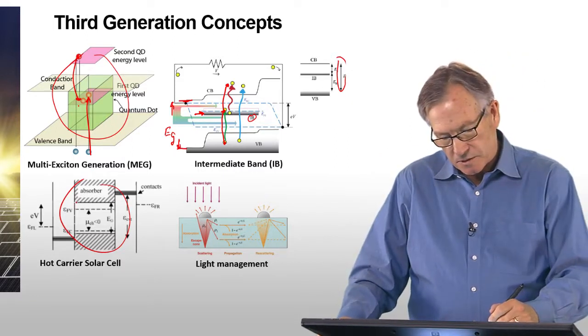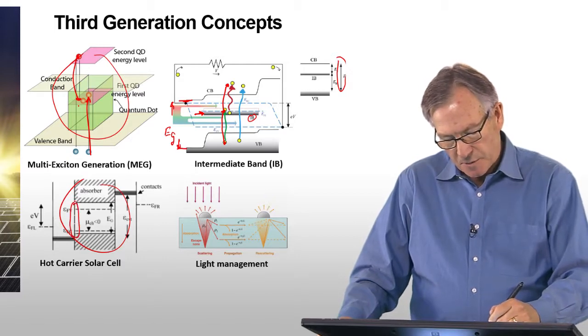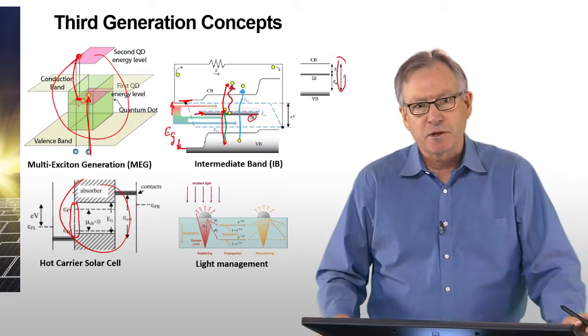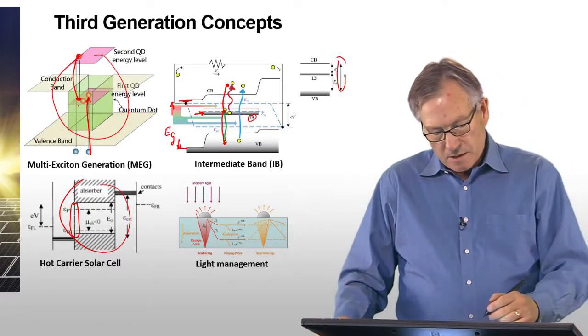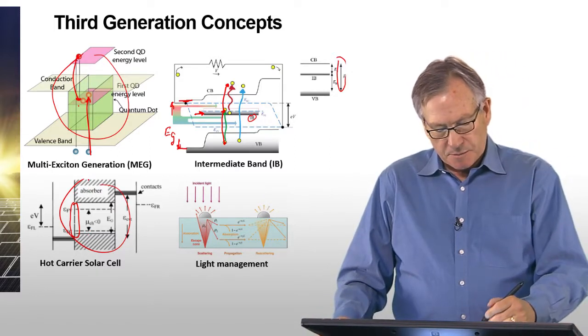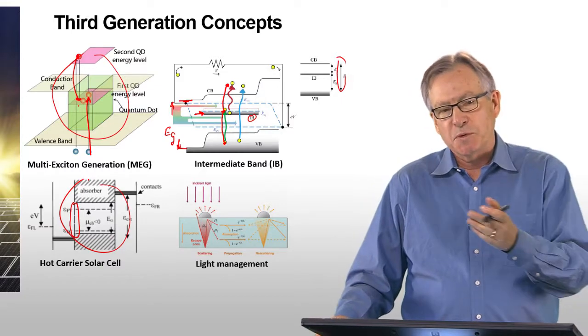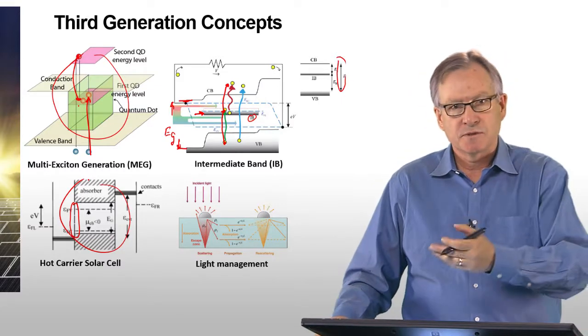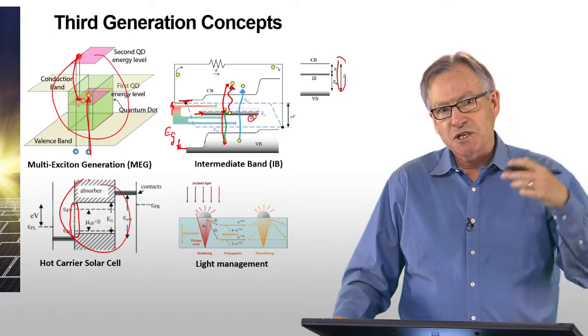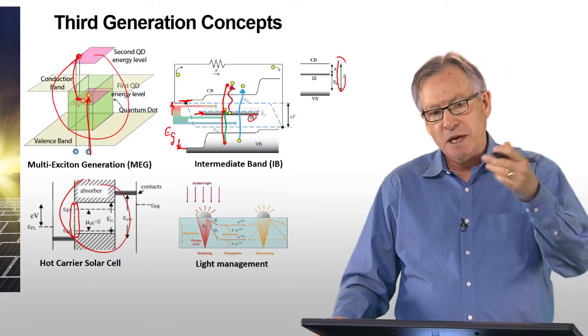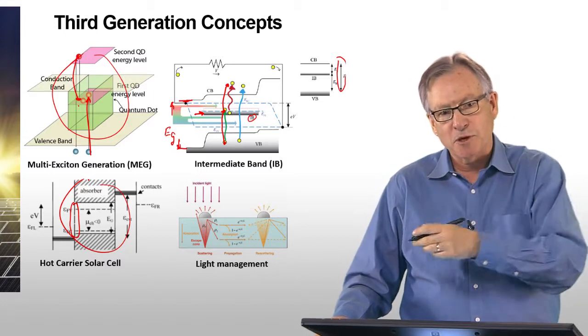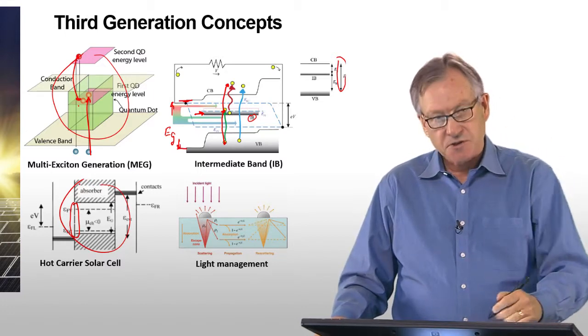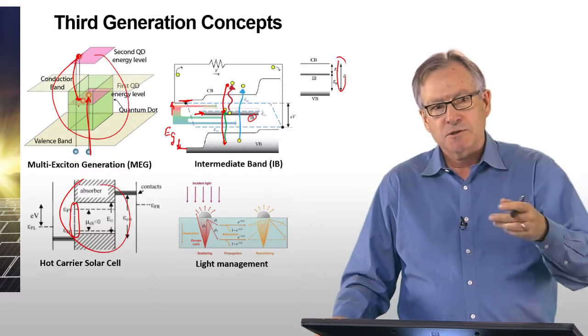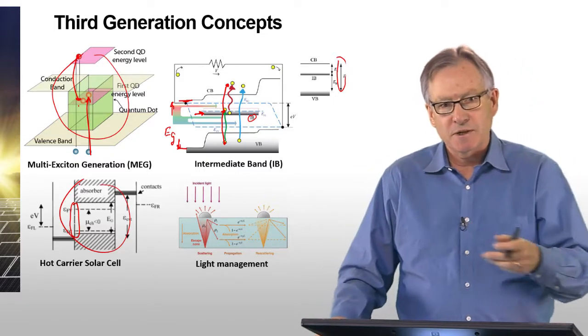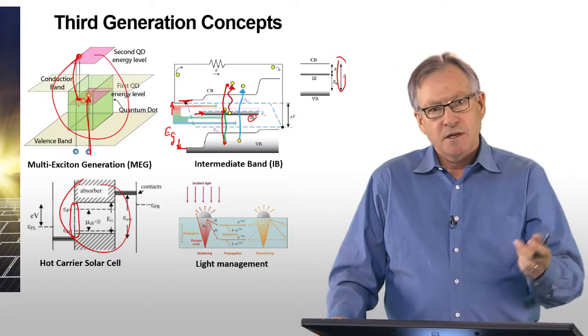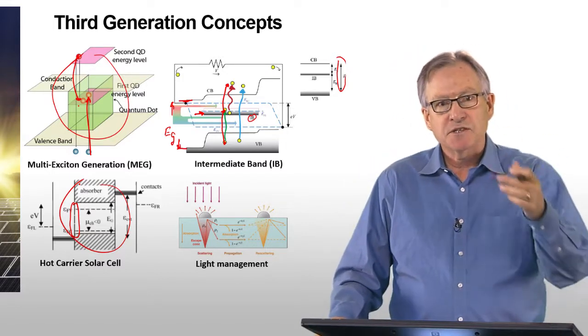The hot carrier solar cell basically consists of a material with a band gap that's relatively small, referred to as an absorber. And this material has a very small energy relaxation. How you realize that is of course the big challenge. But if you could slow down the rate of energy loss of electrons to thermal processes, and keep that energy within the system, you create what are called hot electrons, which means that the average temperature of the electrons as measured by their kinetic energy is much higher than the temperature of the crystal lattice that's the absorber itself.